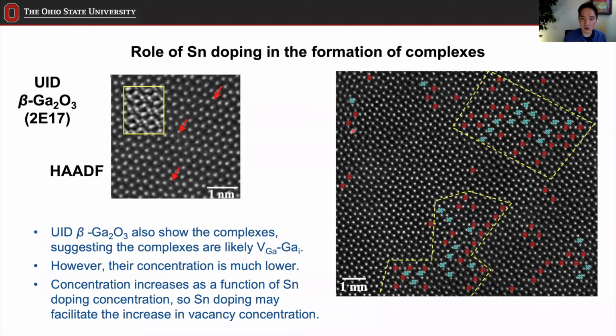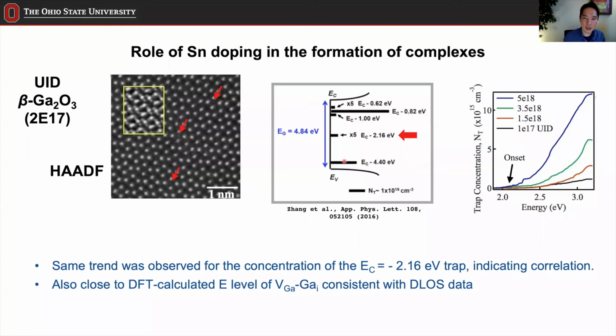The defect concentration, even if the cation interstitial is gallium, not tin. Okay. All right. So that's the conclusion that we can draw from this particular comparison. So this was our STEM experiment showing the increase in the number of complexes as a function of tin doping concentration. Now, if you compare that to what our collaborator has measured using deep level optical spectroscopy, again, this is the way to measure the trap level concentration of trap states.